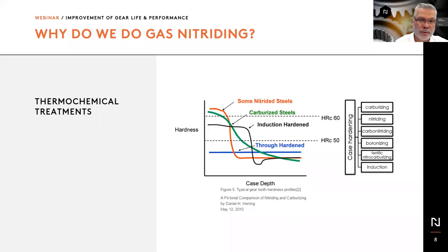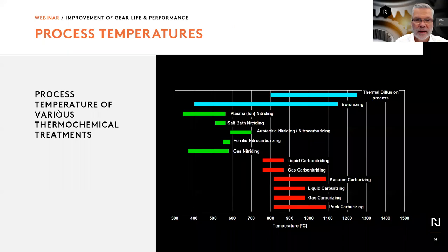So it's a process which may modify both core hardness and surface hardness. And this is really what's setting apart the whole family of nitriding processes and nitrocarburizing processes from other thermochemical processes, which are done at a much higher temperature. As you can see, we are performing nitriding and ferritic nitrocarburizing typically in the ferritic temperature range, whereas carburizing is done above transformation temperature and always involves a quench and temper procedure.